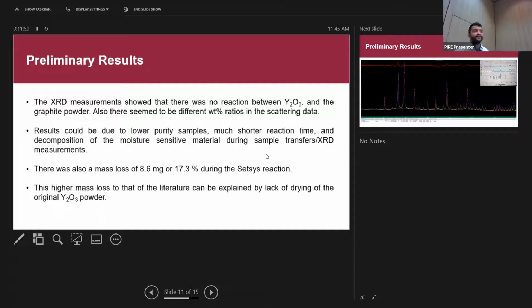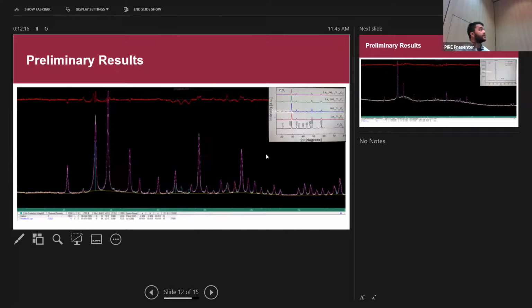And based on discussions that I had with some of my people in the group, they figured that it was based on the fact that there are impurities in the yttria powder that need to be taken care of first. So it needs to be dried and those impurities need to be gotten rid of before we actually do the reaction. It also upsets the 1-to-1 ratio based on the decomposition of those impurities.